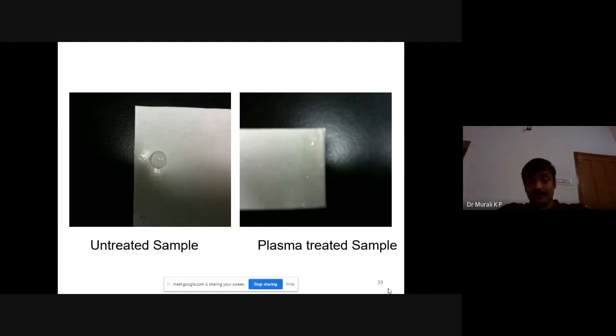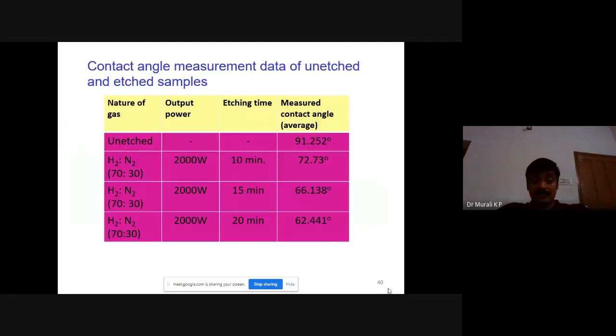In the case of an etched sample, it will spread. The other one will just bead up because the contact angle is very high. So scientifically, we can prove it by measuring the contact angle: for the etched samples, the contact angle will be less compared to the unetched sample.